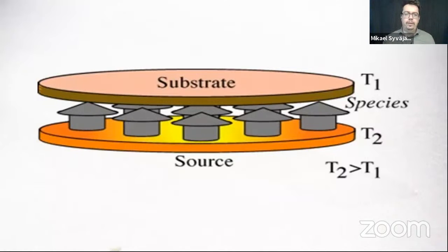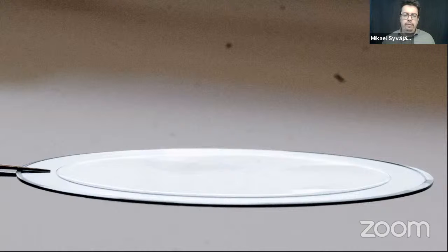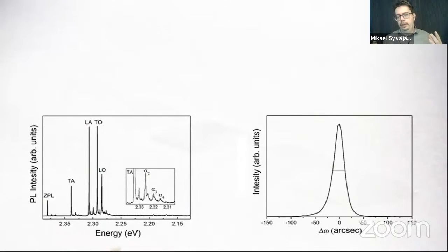So we developed this sublimation epitaxy method, and what we could achieve was thick films on the wafers. Here in the central area, you see a thick film about 100 micrometers thick, grown with this method. And it was a very nice achievement to be able to grow on some wafer size instead of very, very small samples. We studied this material in photoluminescence. There are some characteristic peaks which appear in silicon carbide, and when they appear, this is a nice signature that you have a good quality material. And if the width of those peaks is very narrow, so they're sharp, then that is also a very good indication that the quality is very high.